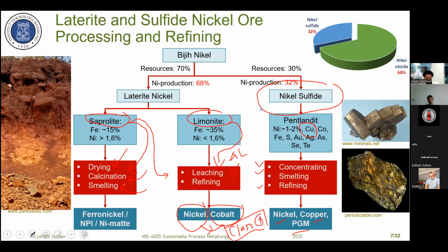The product is for sure pure nickel or nickel pig iron, or we can also add sulfur in the rotary kiln. We can add sulfur in the rotary kiln to convert nickel oxide into nickel sulfide, and then we smelt it in the electric furnace, and then we can remove iron by using, for example, a Pierce-Smith converter, to remove iron by adding flux, silica in this case. And the product is what we call nickel matte.